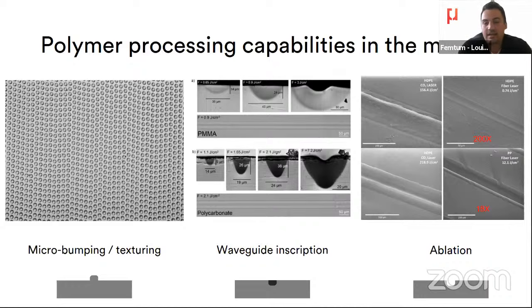And in this case, for some polymers, we can decrease the damage threshold by a factor of 200x when you're at the right wavelength. So let's say for high density polyethylene, the damage threshold is very high. And for us, it's very, very low because of the wavelength and the high absorption.